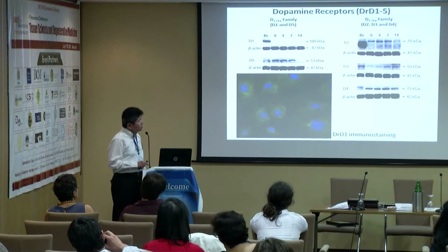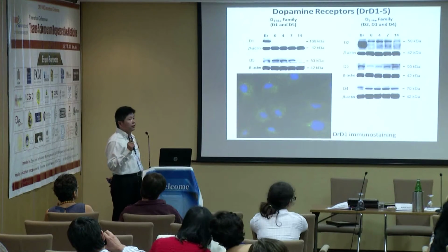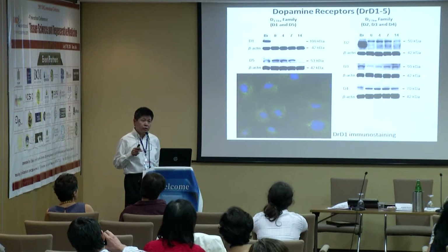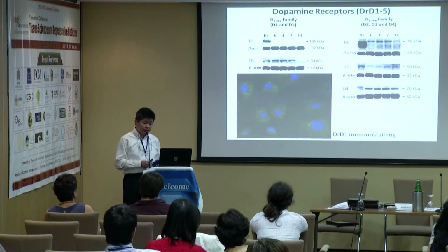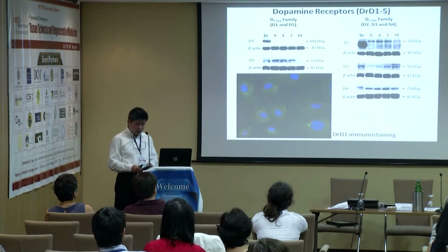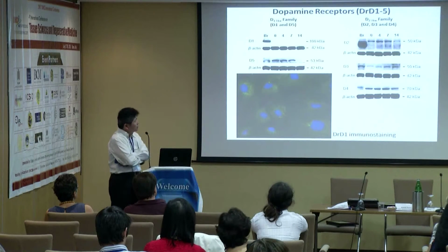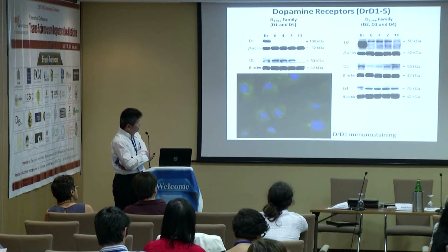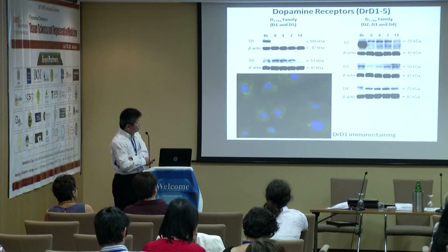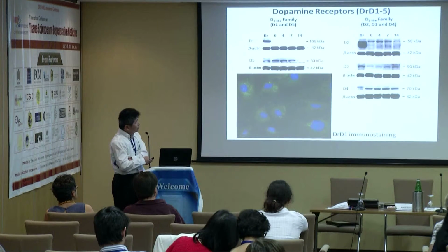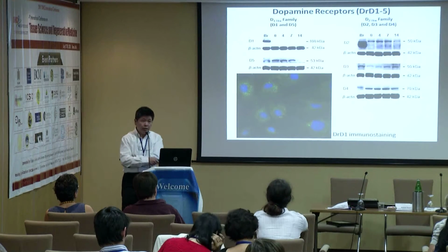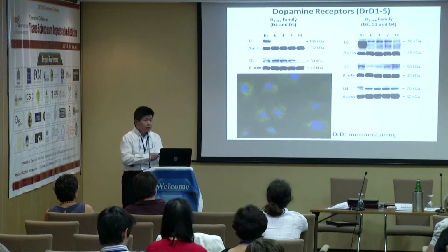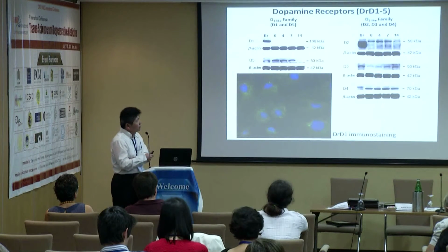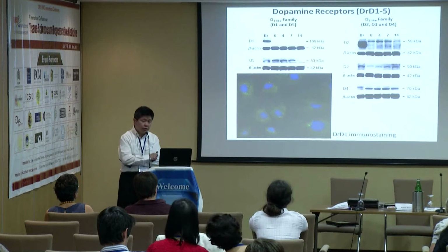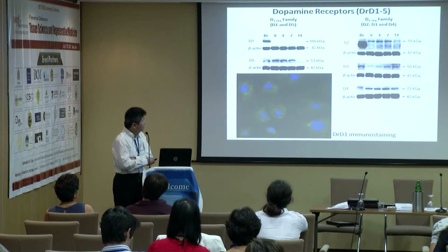Finally, I want to talk about the new system we have, and it's very interesting. When we add the dopamine, it's not just increasing the mechanical strength. We also find that it is helpful for osteogenesis, and we're starting to wonder why and how it happened. So we're in the process at this point of finding out the mechanisms. We have tested some cell lines like MC3T3, and we find they do contain all the dopamine receptors, from 1 to 5, on the bone cells, which is very interesting. So we suspect that maybe some of the leaching monomer dopamine has some stimulating factor on the bone formation as well.